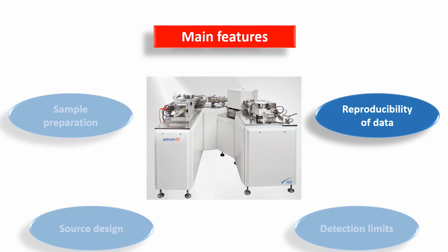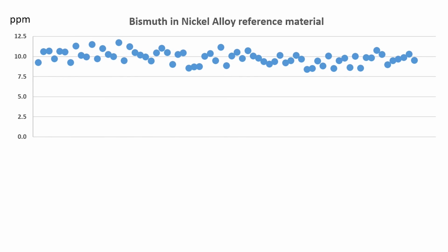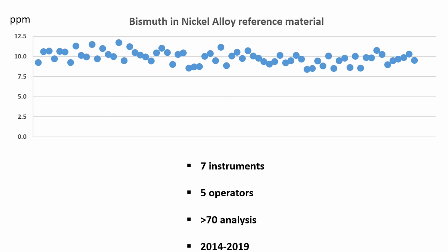And last but not least, reproducibility of data. For quality control, reproducibility of data is paramount, and relying on good instrumental data is a very sought-after aspect of daily analysis. Here we have a set of results for bismuth in a certified nickel alloy sample. The RSD on this set is less than 10%, but the characteristics of this set are very interesting, as the set includes data from 7 different Astrum instruments obtained by 5 operators, being application scientists and engineers at the factory. There are over 70 analyses made over about 5 years from the first to the last data point.